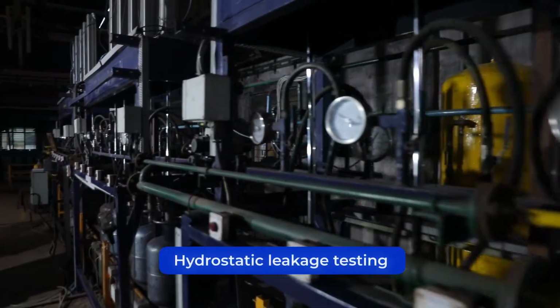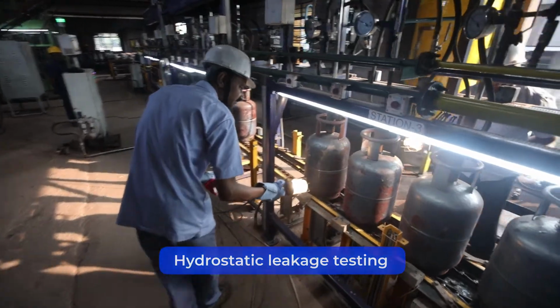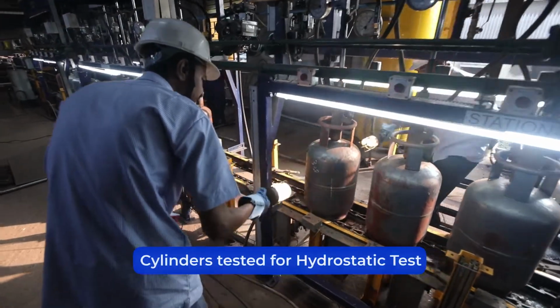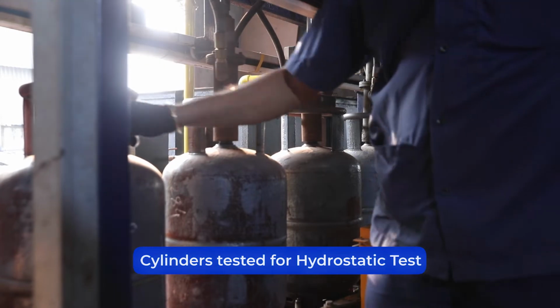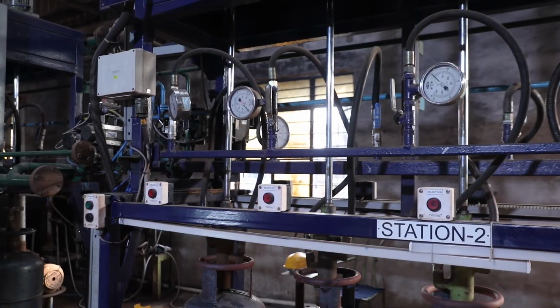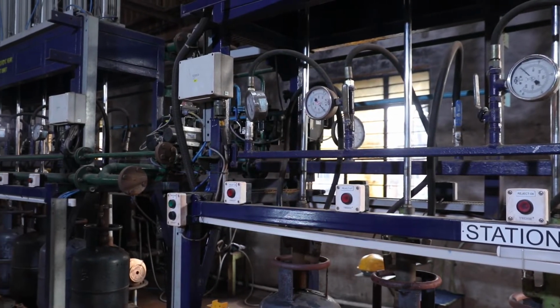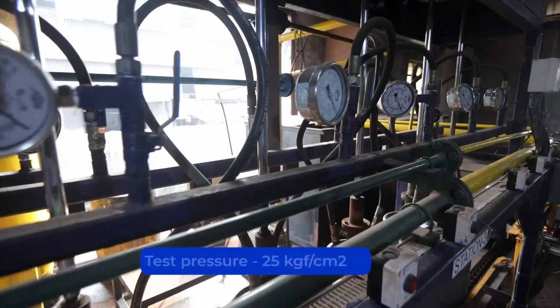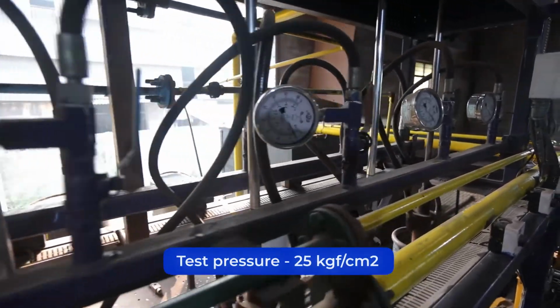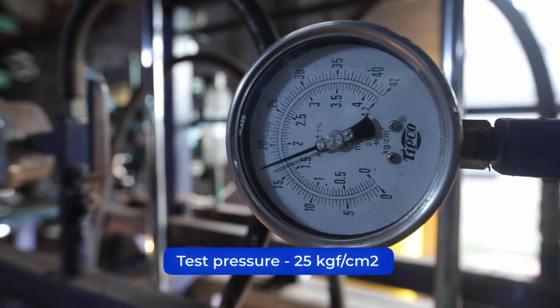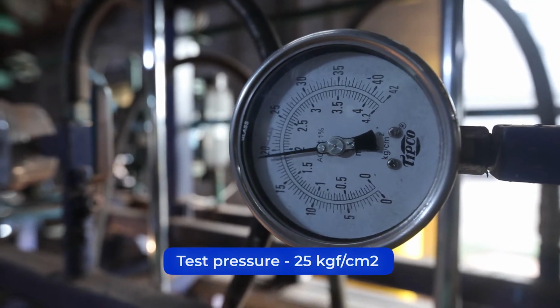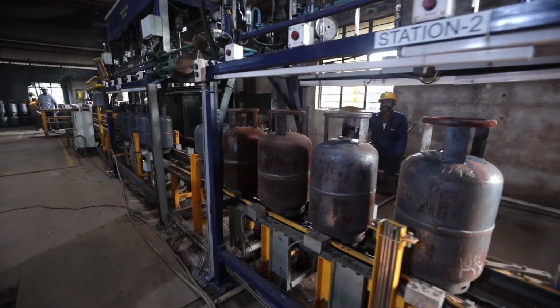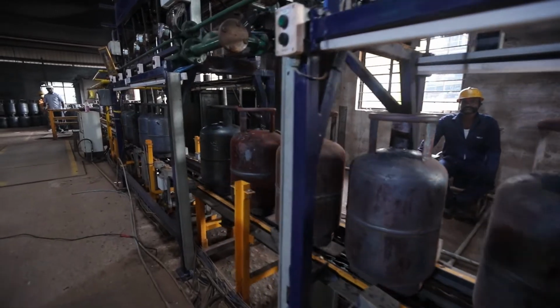Soon after the heat treatment, all the cylinders are tested for hydrostatic test on hydrostatic test station. The testing station is equipped with an auto water filling and evacuating pump and a high pressure pump to attain the test pressure of 25 kg force per square centimeter with an illumination from the bottom side by a mirror.